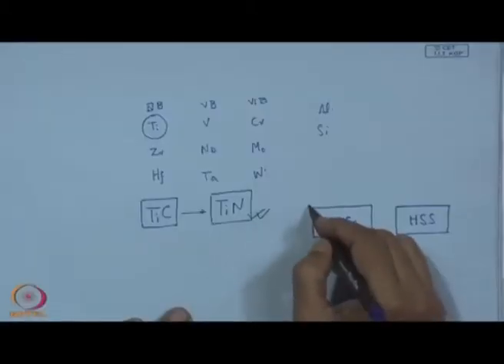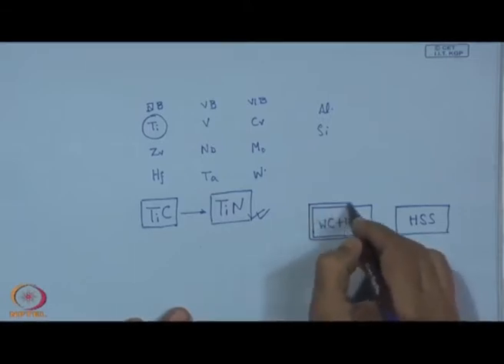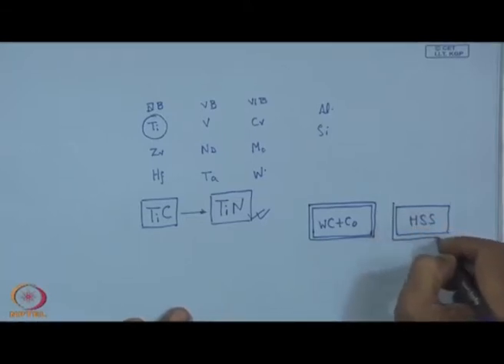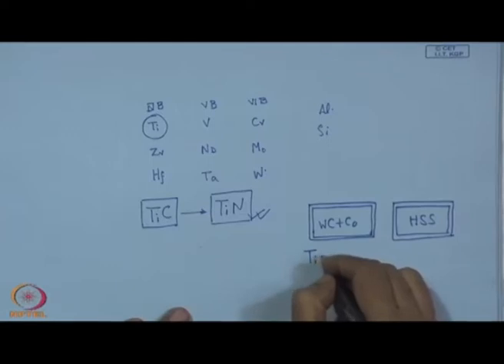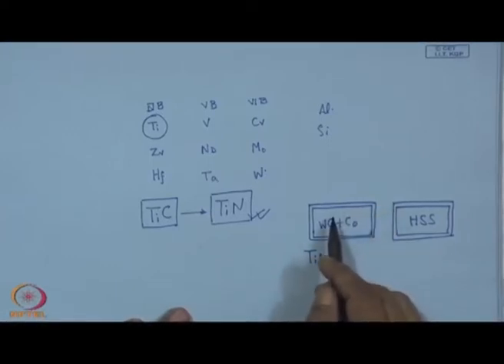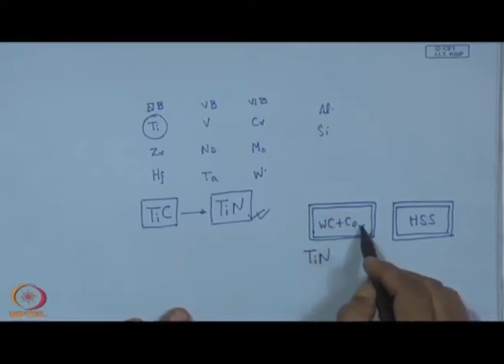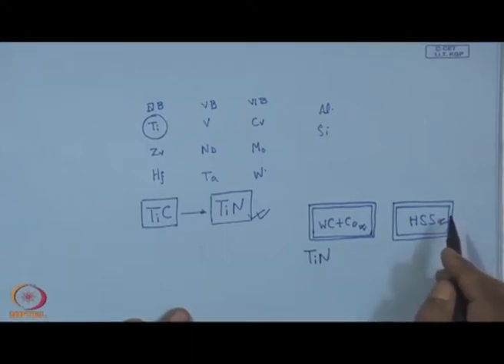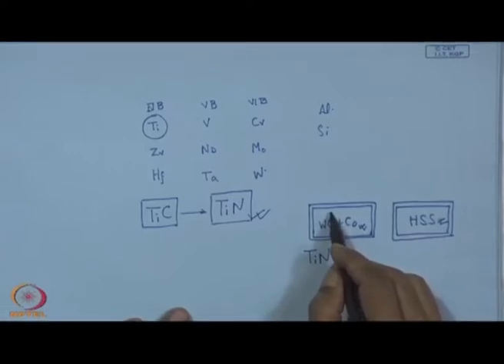Now, by this we can put here a TiN coating, which can give us this kind of augmentation of the property. However, the question here is it is just not the TiN alone. First of all, we have to find out the process which is compatible to this substrate, HSS or tungsten carbide, number 1. Number 2, we can have proper nucleation, growth rate and high nucleation density. These are the essential requirements to be fulfilled in order to have one effective coating, because there are various issues to be addressed. For example, smoothness of the coating, density of the coating, obviously comes the hardness of the coating, and last but not the least, the adhesion of the coating.